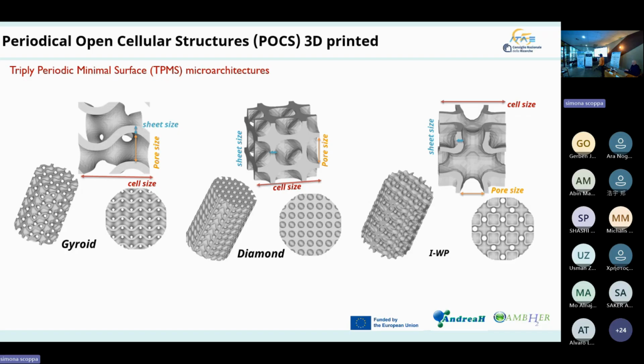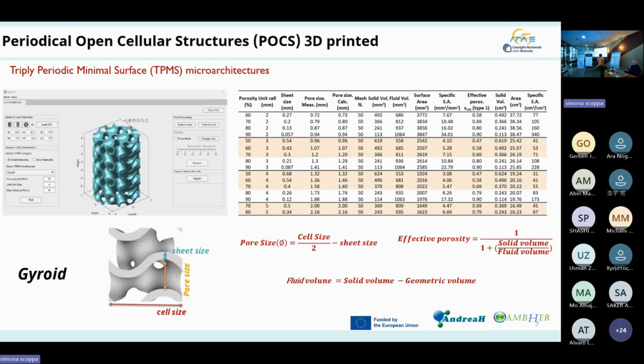In this case, we have a particular type of periodical open cellular structure that is named triply periodic minimal surface microarchitecture, in different geometries: gyroid, diamond, I-WP. We can plan everything, we can design everything, and at the end, we can manage a lot of typologies of structure that can be used as support for our application. So if you look at the first column, we can have different porosity, and especially we can have different specific surface area, just changing cell size, pore size, and sheet size. Everything influences, for example, the pressure drops, and I will show something after.